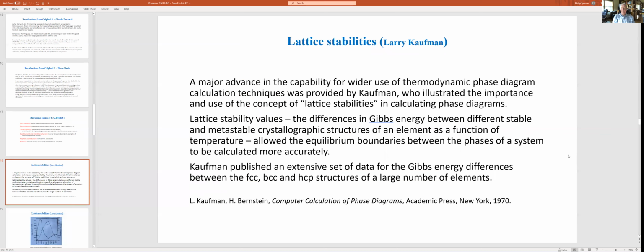So to the lattice stabilities, which Larry Kaufman introduced. A major advance in the capability for wider use of thermodynamic phase diagram calculation techniques was provided by Larry Kaufman, who illustrated the importance and use of the concept of lattice stabilities in calculating phase diagrams. Lattice stability values are the differences in Gibbs energy between different stable and metastable crystallographic structures of an element as a function of temperature. And they allowed the equilibrium boundaries between the different phases of a system to be calculated more accurately.